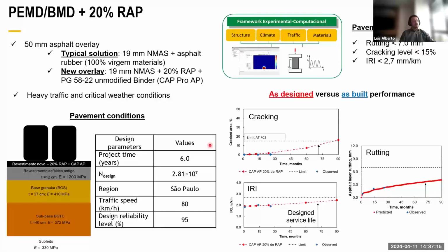So this is the result of the test. When we ran the performance engineered mix design, we only had these red lines. They are the as-designed ones. So for cracking, for IRI, for rutting we did these predictions. Here is the actual pavement design life expected for the road concessions. So in all the simulations, after the optimization, we could see that all the limits were met by our project.